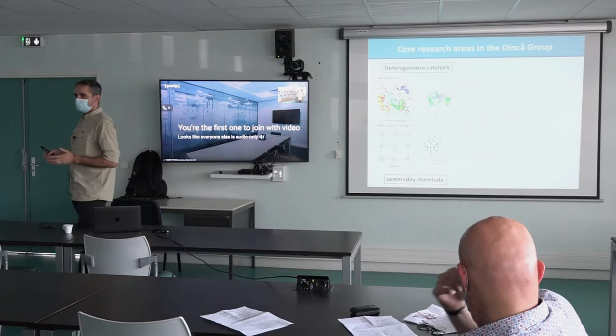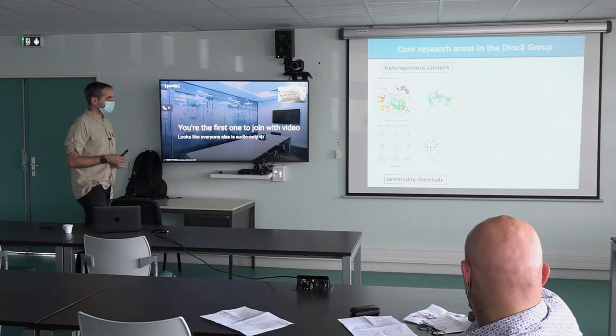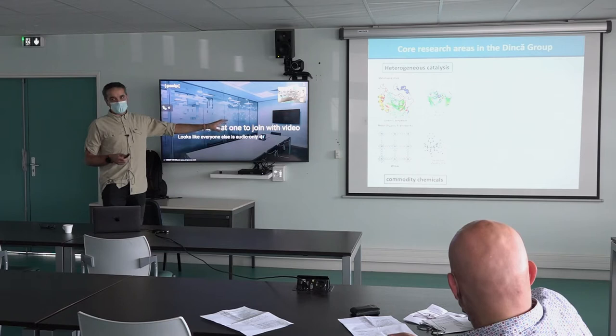Some of these materials can reach up to about 5,000 square meters per gram, which is higher than almost anything out there — higher than even the best high-surface-area carbons. Naturally, people use these to store small molecules: gases, hydrogen, CO2, and other things. My lab, when we started, became interested in learning and exploring the chemistry of these materials.